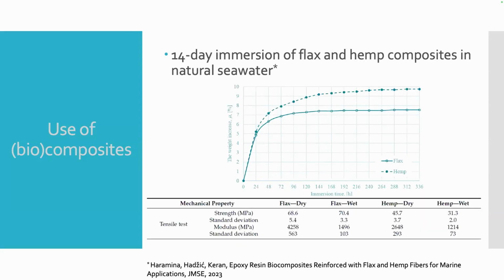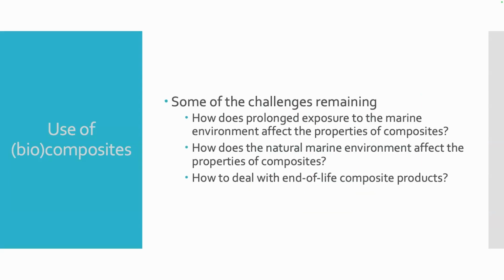I have here selected a study done by our colleagues from Zagreb, Professor Haramina and her team, where they tested flax and hemp composites in natural seawater, to which they were exposed for 2 weeks. What they concluded is that the flax behaves much better than the hemp composites, but what is severely affected is the modulus of both types of composites. So after just these few studies that I have shown here, the questions that we can ask ourselves are: how does the prolonged exposure to marine environment affect the mechanical properties of composites? And how does the natural marine environment affect the properties of the composites?